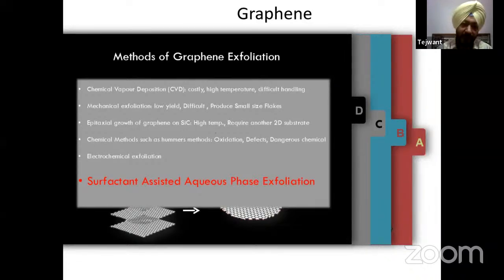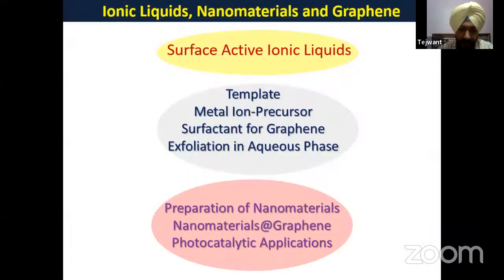But all of these methods have certain drawbacks and limitations, whether in terms of cost, time, temperature, or tediousness of the process. One of the methods which people are using is the surfactant-assisted aqueous phase exfoliation of graphene. If we use a surfactant for exfoliation, it means we exfoliate the graphene from graphite in aqueous medium by using a surfactant. This is a very green process. So now you can come to know what I am going to talk about today. I will talk about ionic liquids, which we are using as templates, metal ion precursors, or surfactants for exfoliation of graphene in aqueous medium. Further, the same ionic liquids have been used for the preparation of nanomaterials singly in aqueous phase, or nanomaterials appended at the surface of graphene.